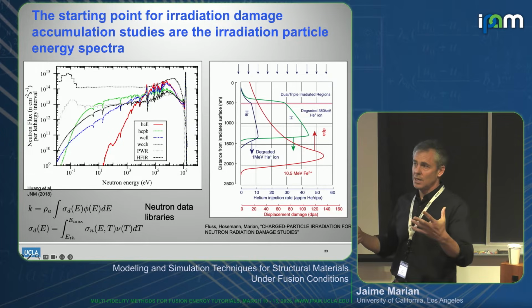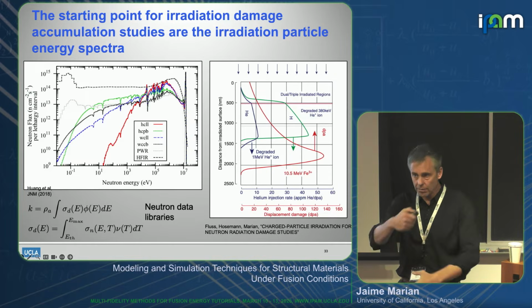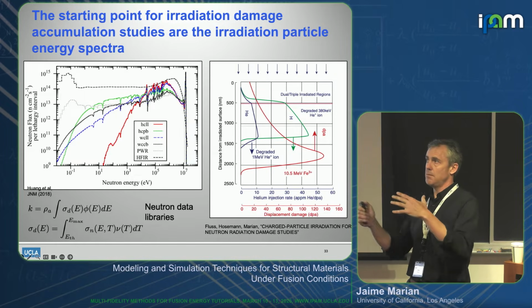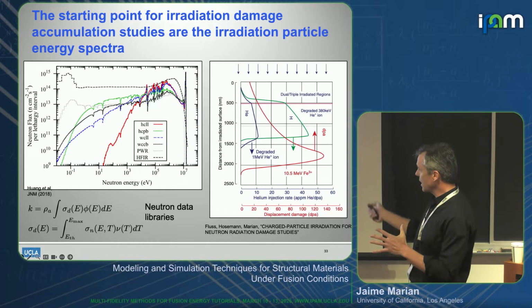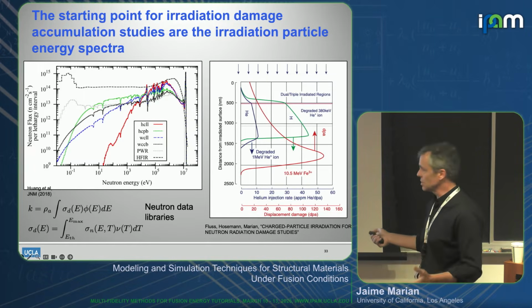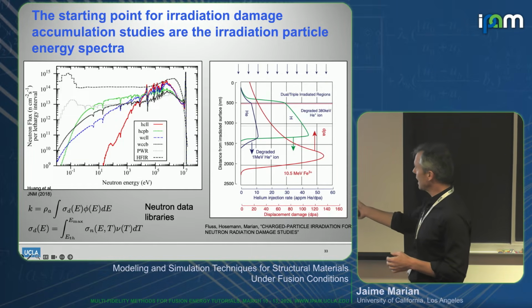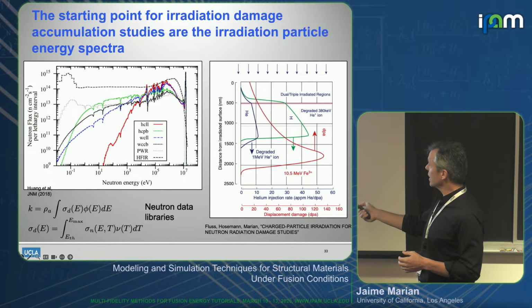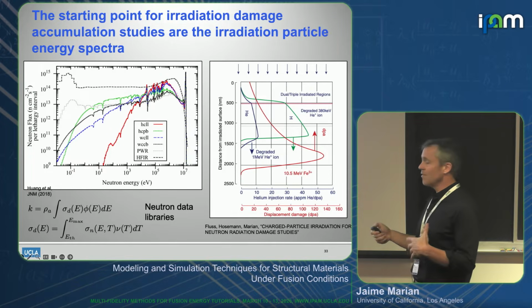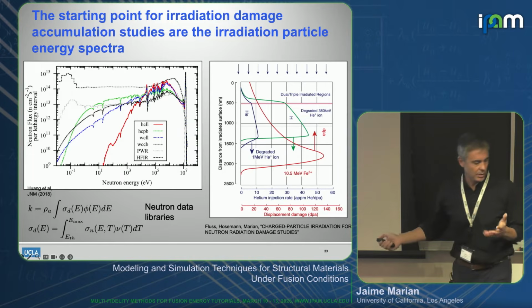So you have to take into account the near surface effects and deconvolve those so that you can match what you get in an ion beam experiment to what you get in a neutron experiment. Again, very challenging. We can co-implant helium, hydrogen, and damage in such ways that the ratios between the three reflect what a presumed fusion reactor would have. So we can do all these things.